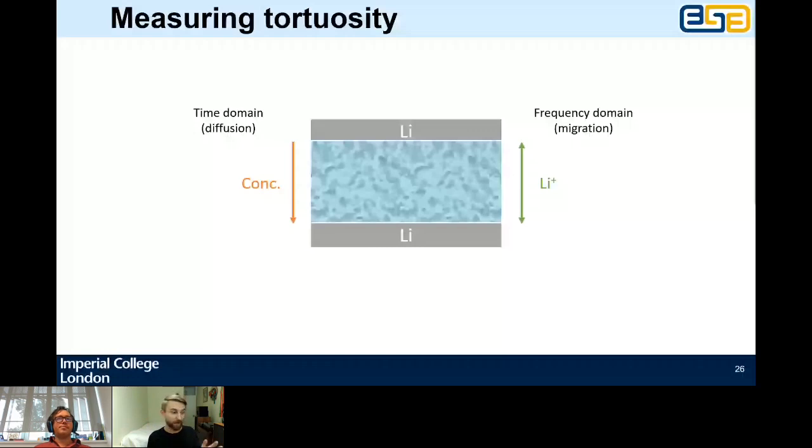One is the first time domain approach again, but you've now got your freestanding electrode in the middle, okay, the orange region, but you have to put, because it conducts electrons, you have to put a separator on either side so it doesn't just have a short circuit of the electronic current through the system, okay? And you have to actually have a model of this because the electronically conducting solid of the electrode can also see the potential field and will distort it.